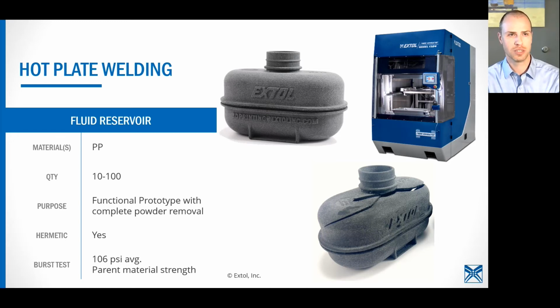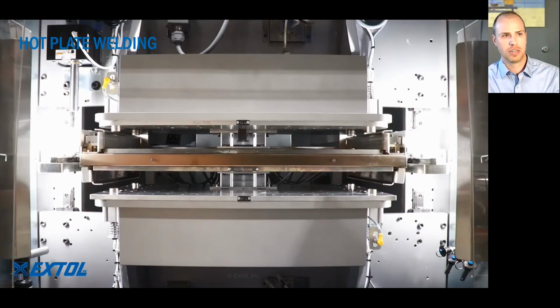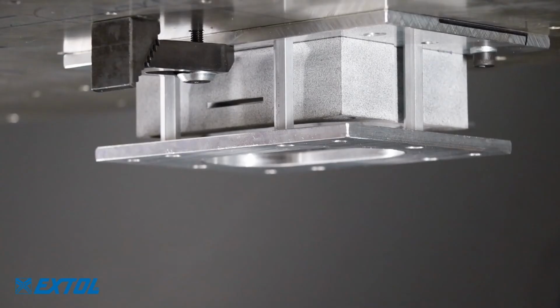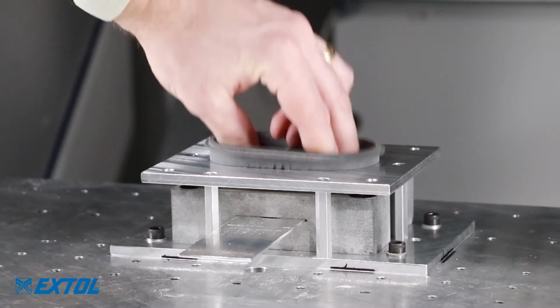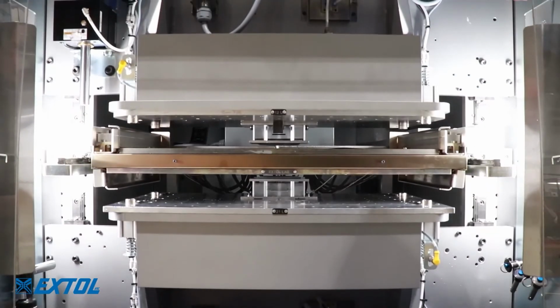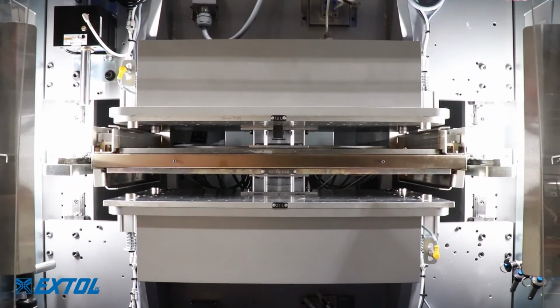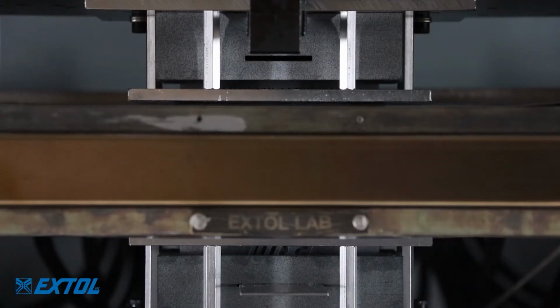So this is what we expect to see in molded parts, and we see the same thing in welding MJF polypropylene parts as well. Here's a video of that welding process. The MJF parts go into the fixtures. The weld ribs on those parts then touch off on this horizontal plate, which is about 500 degrees Fahrenheit. And that's what is melting those weld ribs before the parts are joined back together.